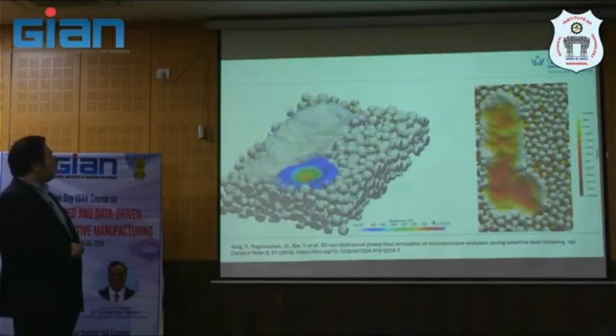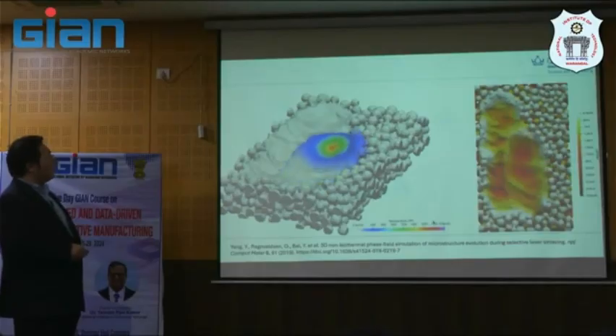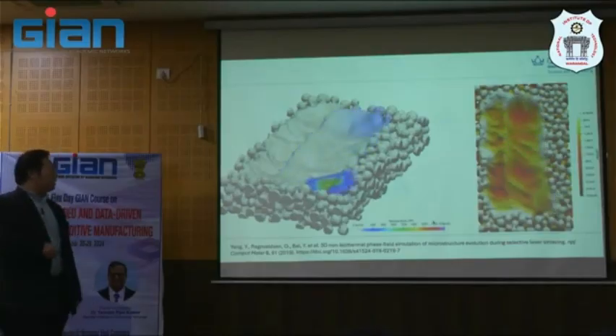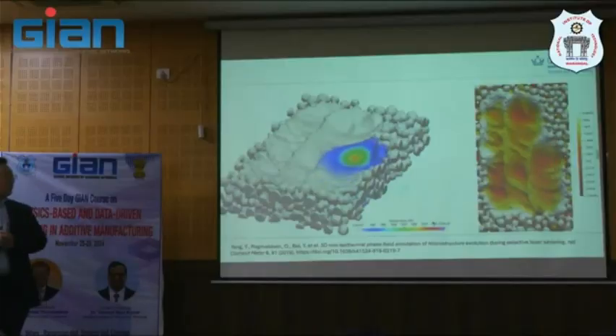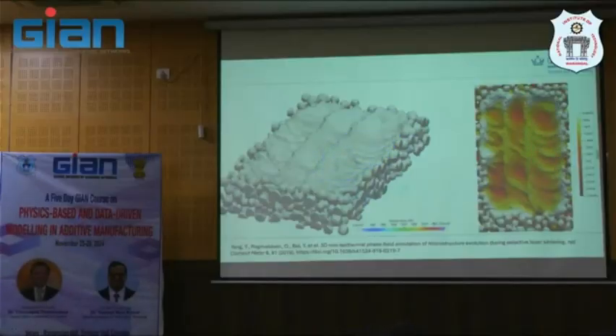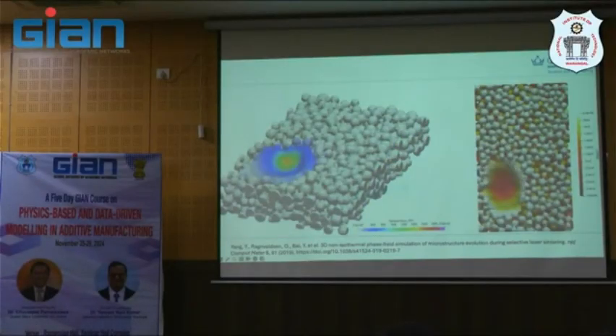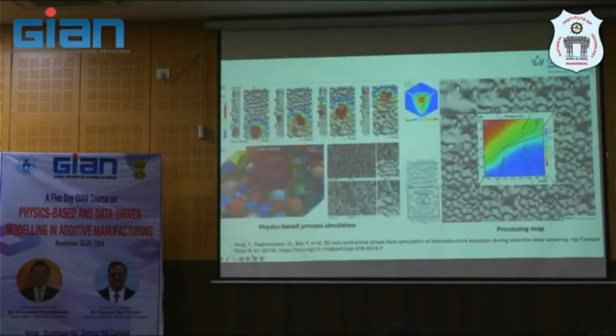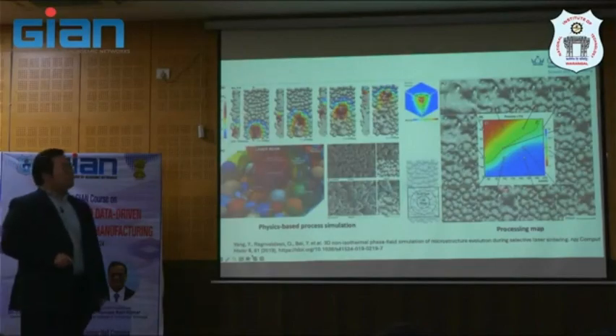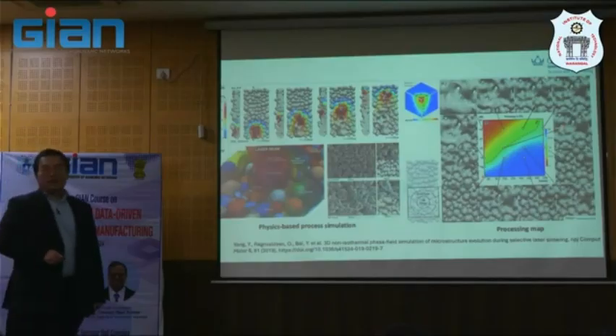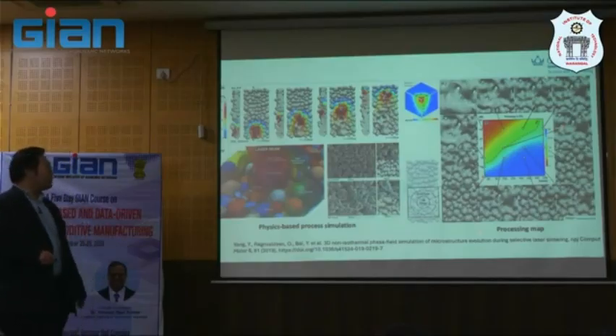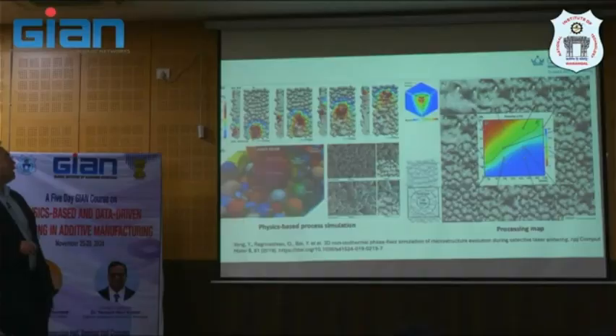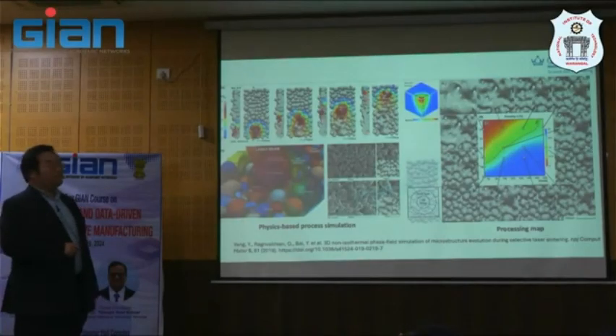So you see, if you scan these 3 tracks here and try to predict the evolution of the microstructure in terms of porosity, what you see is this one. Yes, you can produce or create the process map PV, the same as you saw before. This is the processing map, and you can see that at different conditions, this model actually shows, 3D simulation.